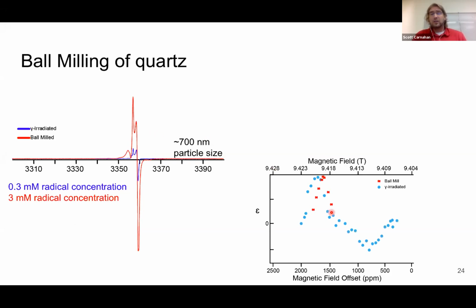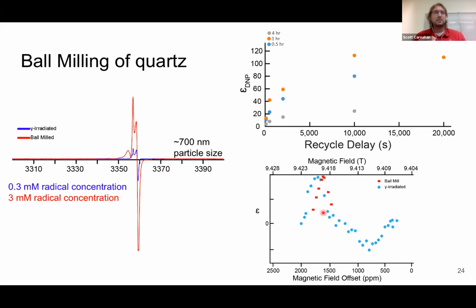We put it in, and you can see that it has a fairly narrow positive maximum. We were able to test several different ball milling procedures to try and optimize this, and we got up to a maximum DNP enhancement of around 120. As you can see, this is a bit lower than the 400 we got through gamma radiation. We think that's because gamma radiation caused more evenly dispersed radicals through the sample, whereas ball milling is creating clusters of radicals, which makes it a less efficient DNP polarizing agent.